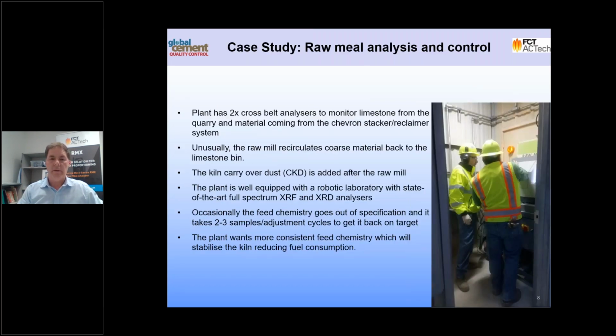So what I have here is a case study about where an online raw meal analyzer has been installed into a very progressive cement plant in the USA. This particular plant is producing around 1.7 million tonnes per year, and they want more consistent feed chemistry to improve their kiln operation, mostly because they've got a pre-blend heap system, which creates off-spec material each time that they change from one heap to the next.